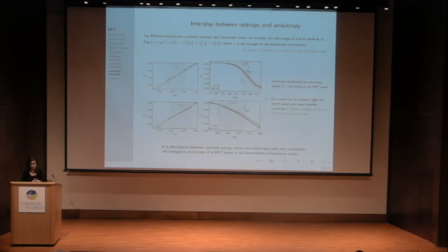And in this model, they show that depending on the strength of the anisotropy, if we take the asymptotic limit where the anisotropy is at its strongest value, then we will suppress the BKT phase fully. And in the other limit, if the anisotropy is decreased to 0, then we would suppress the ferroelectric phase fully, since we will be in one-to-one correspondence with a 2D XY model.